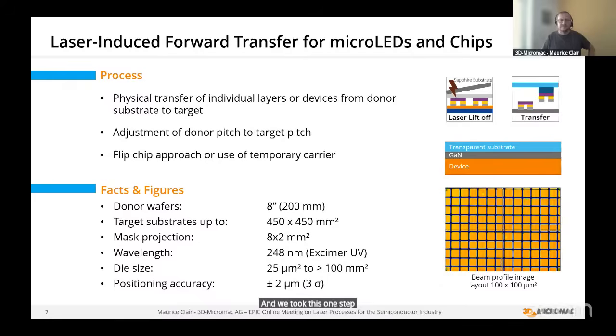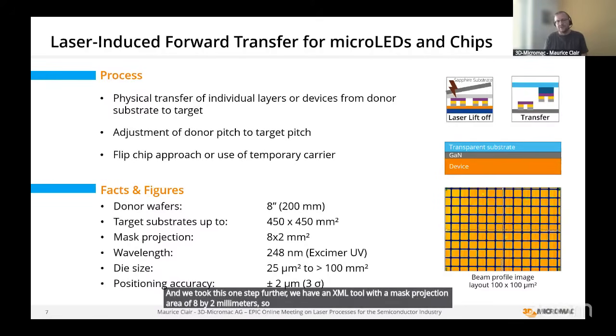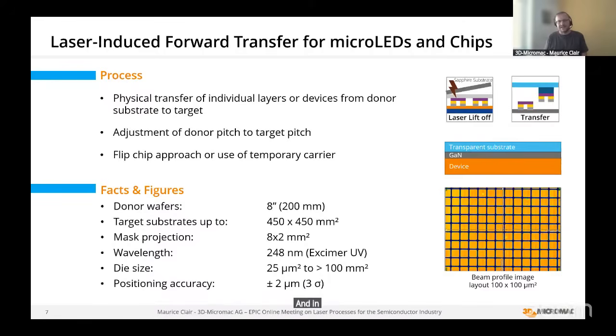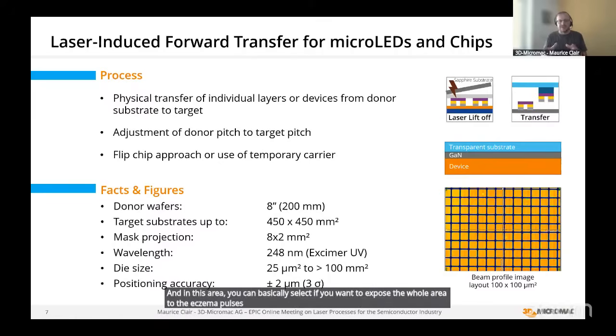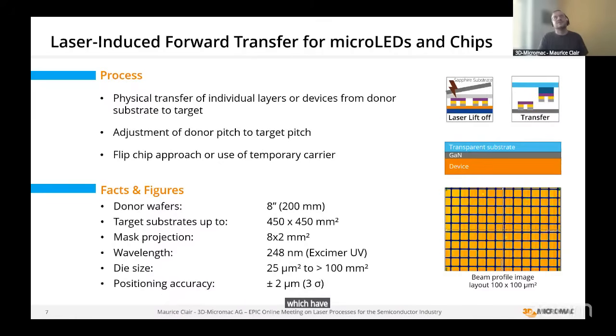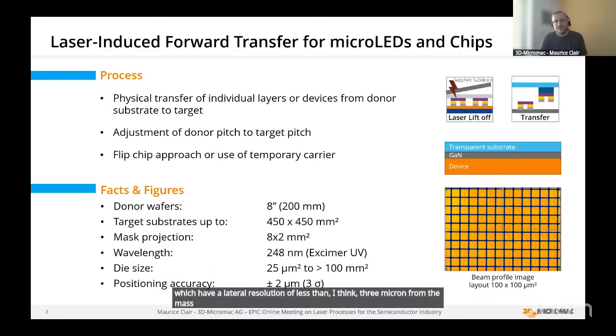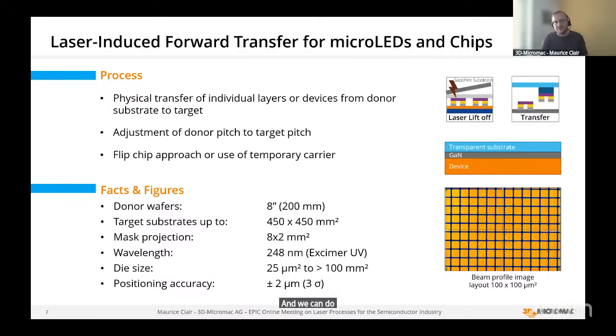We have an excimer tool with a mask projection area of 8 by 2 millimeters, so 16 square millimeters per individual laser pulse. And in this area, you can basically select if you want to expose the whole area to the excimer pulses, or if you just want selective areas which have a lateral resolution of less than, I think, 3 micron from the mask projection. And we can do all of that with a positioning accuracy of plus minus 2 micron.